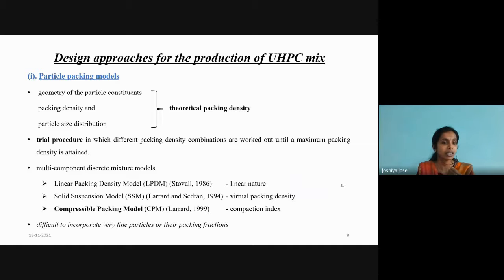So there are basically three mixture models, and the very first one is the LPDM, linear packing density model, which was further developed into the solid suspension model, which uses the concept of virtual packing density. Virtual packing density is the maximum density which can be attained when each of the particles is placed one by one. And further development was the compressible packing model, which considered the process of compaction, which also influences the packing density of the mixture. They presented a term, the compaction index, which accounts for the compaction effort.